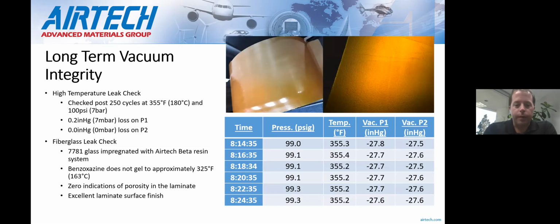So as Greg mentioned, we have been doing long-term vacuum integrity tests as well as dimensional tests on our test tool. After 250 autoclave cycles, we took the tool up to 180 C and 7 bar, and we shut off the vacuum. And what you see here is the raw autoclave data.